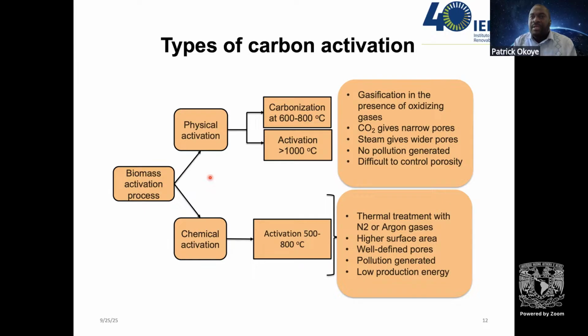And then the problem is that the oxidizing agent used in physical activation makes it very difficult to control the porosity. And if you cannot control the porosity very well, then it becomes challenging to have an application, because depending on the type of application, the surface area is very important as well as the porosity. And if you use steam to do an activation, there are higher chances that you lose some of these functional groups that may contribute in one way or the other to enhancing your process.